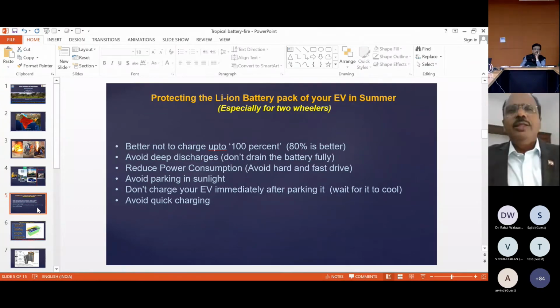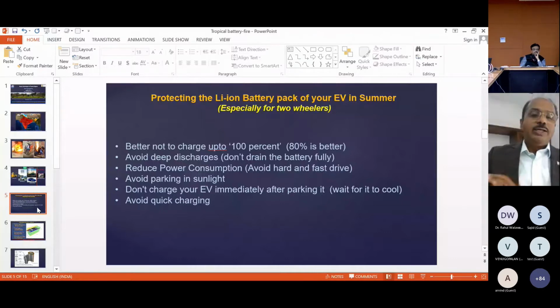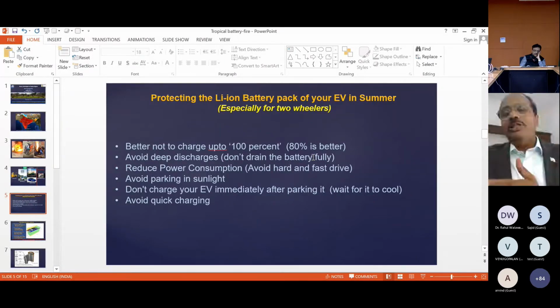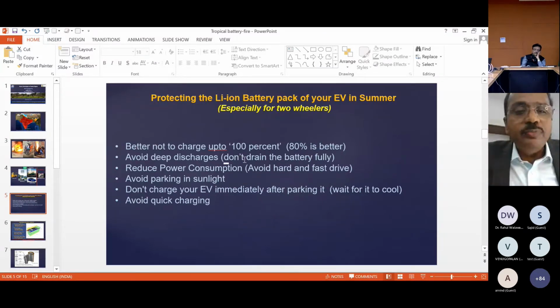So temperature is the big problem, even at outside temperature, and if you don't have proper thermal management, then it is going to blow up. So what I suggest for the two-wheelers is that it's better not to charge up to 100%, because the moment you charge 100%, you're taking lithium from the cathode and giving it to the anode, and your resistance on the cathode side is increasing, and you have resistive heating, that's Joule heating, I squared R, and it's going to heat up. And avoid deep discharges and reduce power consumption, avoid hard and fast driving, do smooth driving, and avoid parking in the sunlight, because the sunlight keeps adding temperature rather than cooling, and although your room temperature is 50, it doesn't cool down, so the inside temperature keeps increasing, and once it crosses 100 or so, then you have all these problems.